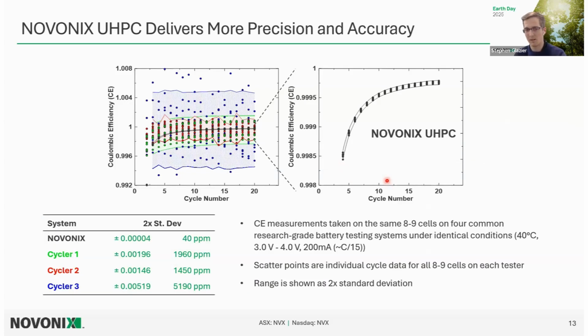What does this mean when we compare to other cyclers? Why, do you need UHPC to do this? We look at coulombic efficiency tested on a number of other research-based good precision cyclers. We can see that the spread in coulombic efficiency of identical tier 1 cells that are tested is orders of magnitude better. So if we take 8 or 9 tier 1 cells and test them and look at the spread of coulombic efficiency, notice the scale here is really blown up.